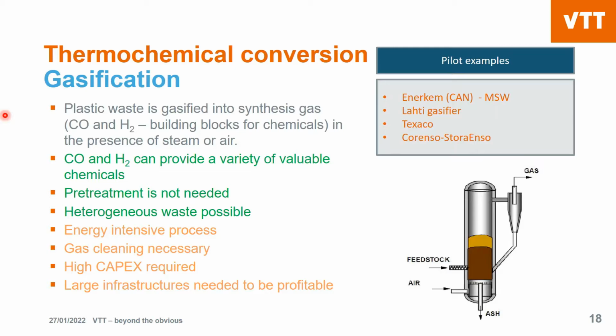Pre-treatment is not needed in many cases because gasification is very flexible on the feedstock quality, and heterogeneous waste is possible. But this process is very energy intensive, and gas cleaning, which means the gas that comes out of this process can be very dirty, so you need to have a gas cleaning step. It requires a lot of investment, high capex, and in order for gasification to be profitable, large infrastructures are needed. So these systems cannot be made in small scales because they are not really profitable.